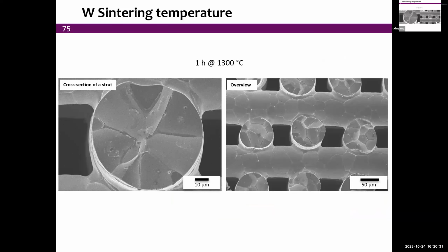And again, if you watch, as I go to 1300 degrees C, we see even coarser grains. This is now becoming oligocrystalline. We have maybe 10 grains in the cross-section, or maybe 5 or 6, as shown in the cross-section here. So that will now become somewhat anisotropic in its properties.